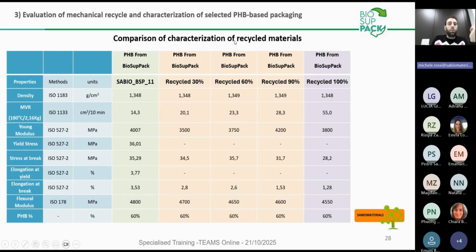A table of comparison. On the first green column, Sabio BSP 11 is the material obtained before, and the following three, 30, 60, and 90%, are the characterization of the material with different percentages of recycled material inside. The last column is the 100%. For all of these materials, more or less, the density stays the same because the formulation used is always the same, and even the PHB content is maintaining the same value.